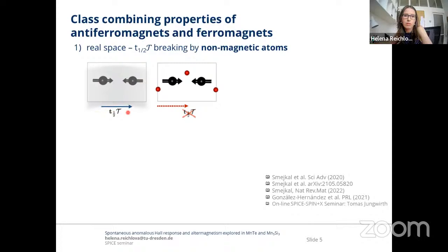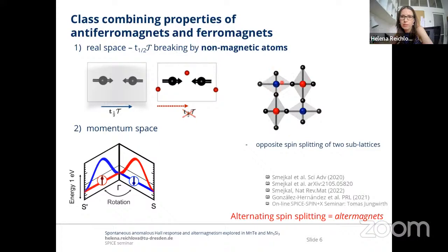In that case, we however keep the rest of the non-magnetic atoms as a homogeneous uniform background. And in some materials, by placing and considering the non-magnetic atoms, as for example in these positions, we see that the same exercise will not give us the same result, because when we now flip the arrows and shift it by half unit cell, we do not recover the same picture, and therefore the TT symmetry in that case is broken. And this is a pretty fundamental thing, because when we then look into some real materials, we see that the local crystal electric field, which is present there because of the non-magnetic atoms, is not connected by the translation or inversion, however, by a rotation.